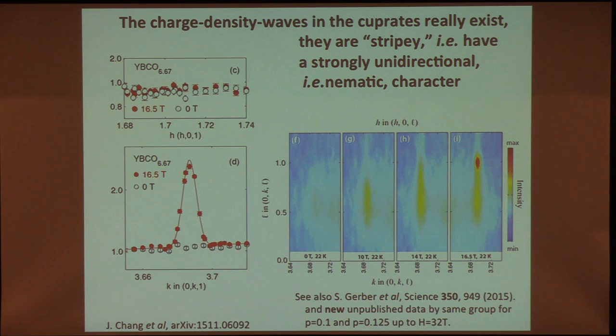Is it aligned with the chains or perpendicular? The ordering vector goes along the chain direction. So the stripes are perpendicular to the chains. I should say this three-dimensional ordering was discovered using pulsed fields by my colleagues at SLAC, but this beautiful detailed study could only be done in static fields, so this unidirectionality was first discovered in this paper by Johan Chang.